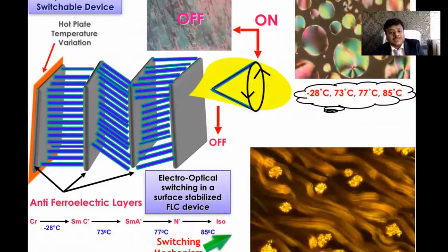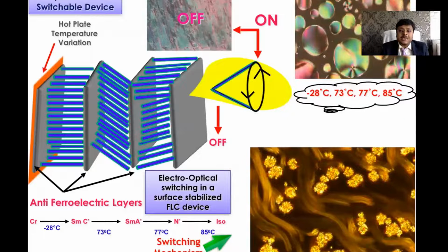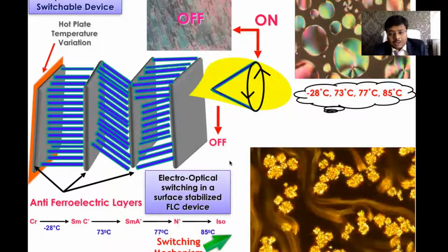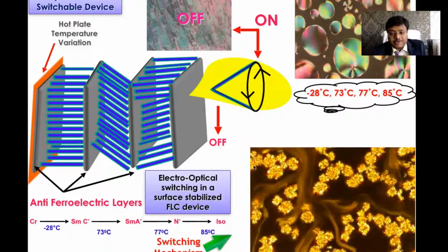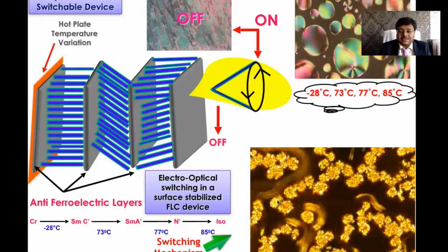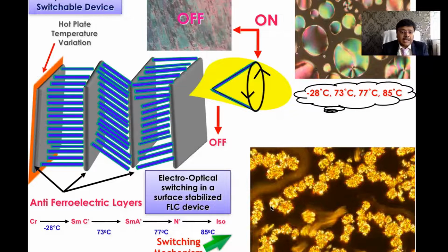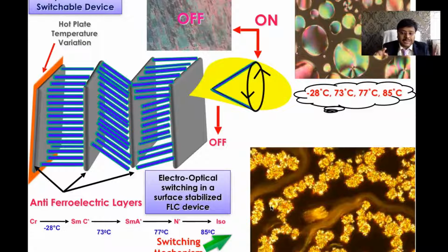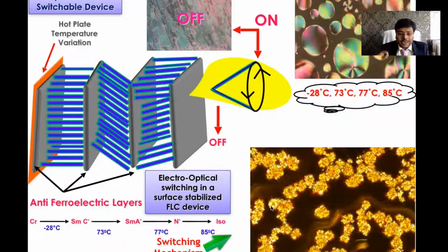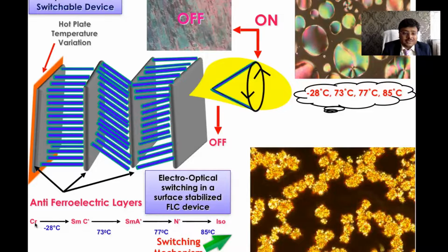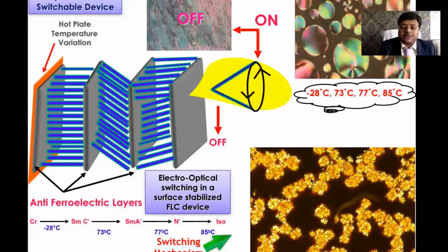It's called an electro-optic switchable device, in a surface stabilized ferroelectric liquid crystal device. You can see first what we did when we inserted our hybrid liquid crystal and nanomaterials inside the cell, and it is just passing through inside the cell. With temperature, of course, we apply a bias voltage of 0.5 volt, and we also connected a temperature controller. You can see different phases: crystalline, smectic C, smectic A, nematic, and isotropic, and a different kind of switching mechanism with that temperature variation. You can see it is completely stabilized, the hybrid composite of liquid crystals mixed with the nanomaterials is in a stabilized state.